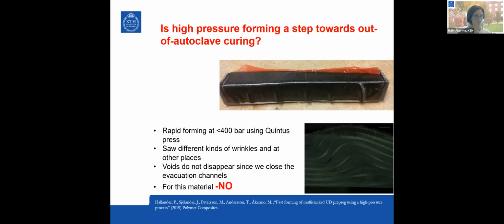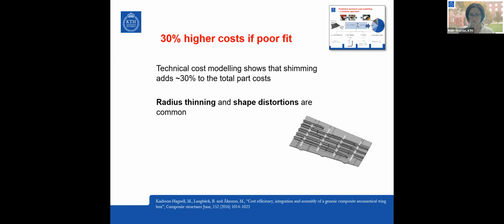So that was the first part, about finding a processing window for the automation technology you have applied. When you had that, I said that you need to ensure that you have a good robust process and that the different parts fit well together. I'm basing that on the predictive cost modeling tools that we developed, where we also looked at the assembly process. And when you have an assembly like this with a lot of different spars that have to fit well together, it's easy that small shape distortion or radial thinning will make the fit not good enough, and you have to go to other activities to ensure that they fit within aerospace standard. And we saw that actually, if you have to do this, it adds up to 30% of the total part cost. So this is important, of course.